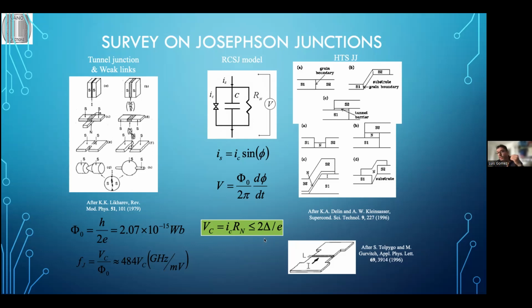Now once you determine the characteristic frequency, then you have the oscillator that will have a natural frequency of oscillation at a different value. As you can see here, it can be quite large, depending upon the level of characteristic voltage. Most people in applications want to go to the highest possible oscillating frequency. There is actually a technological gap. We don't have a convenient system that will give you high oscillation at a higher frequency, that can even be an antenna for these high frequencies, or a transmitter for these high frequencies.